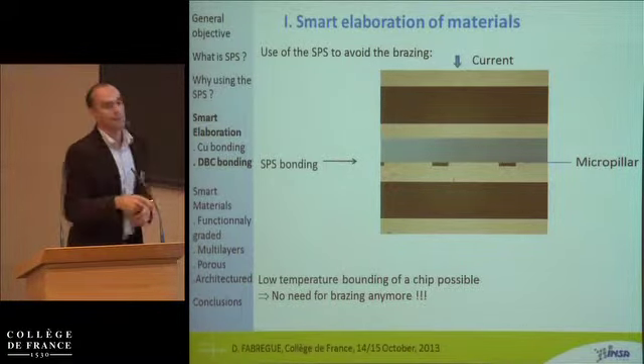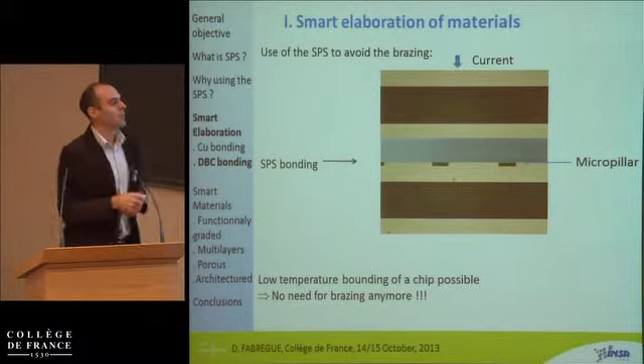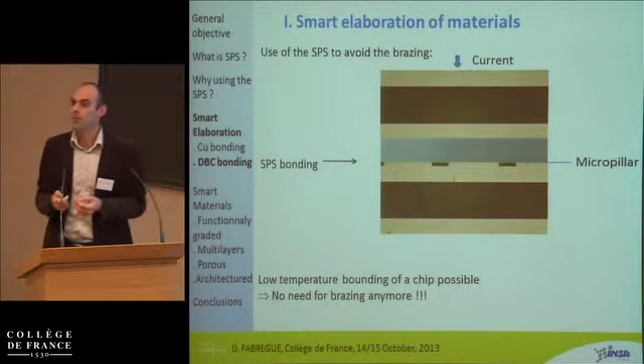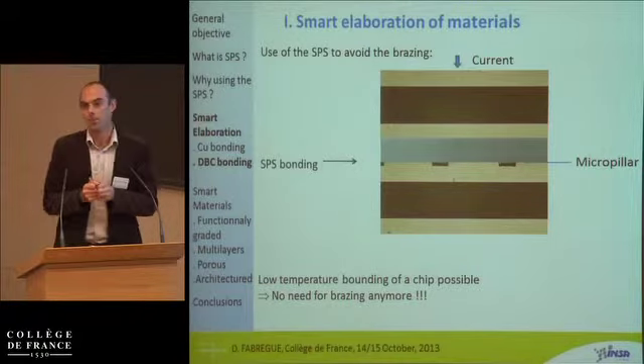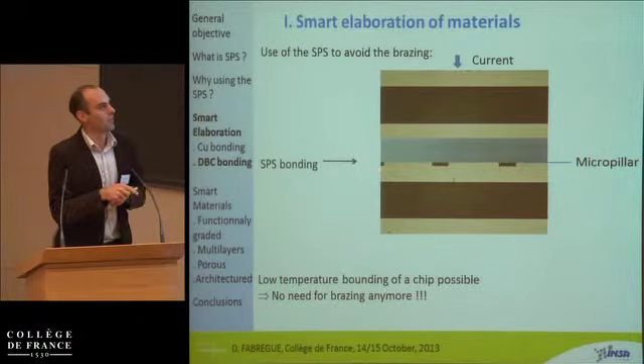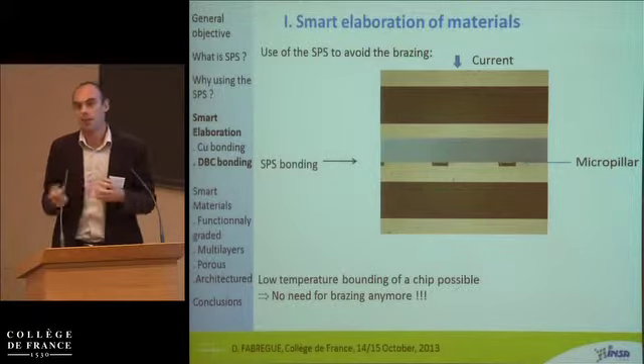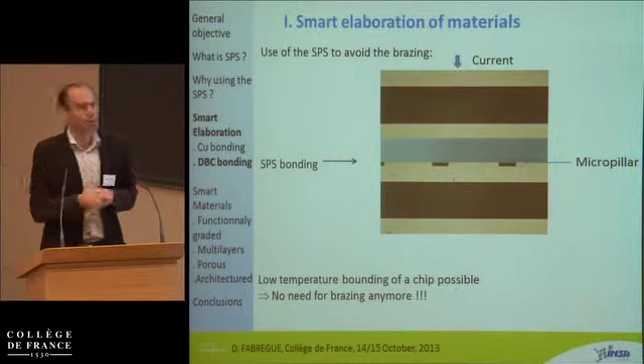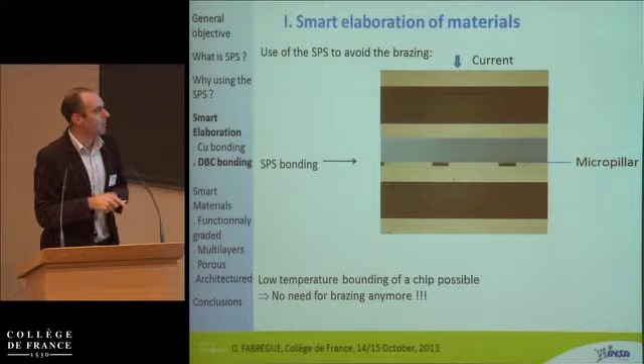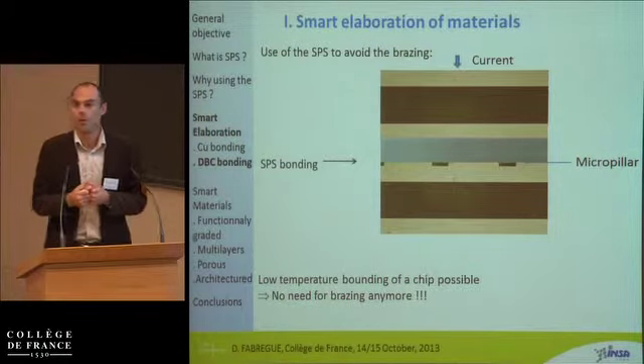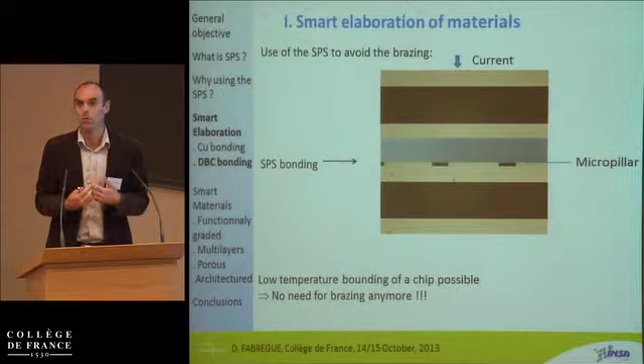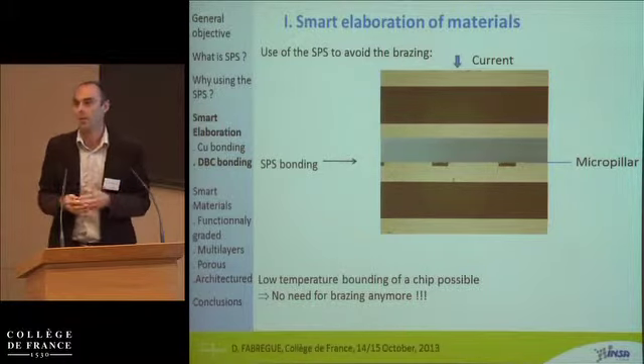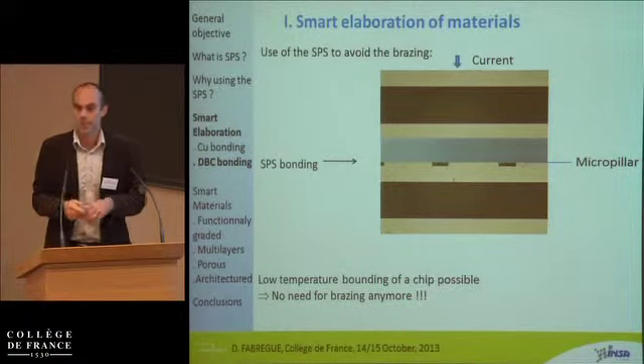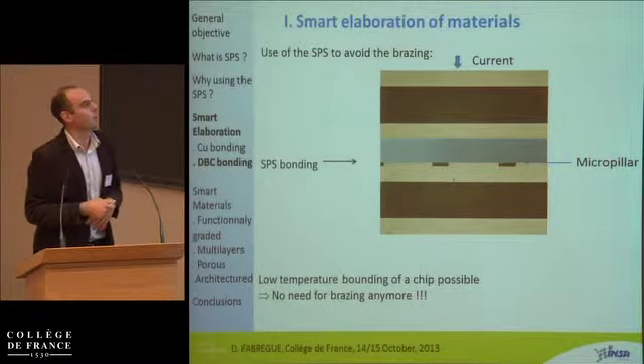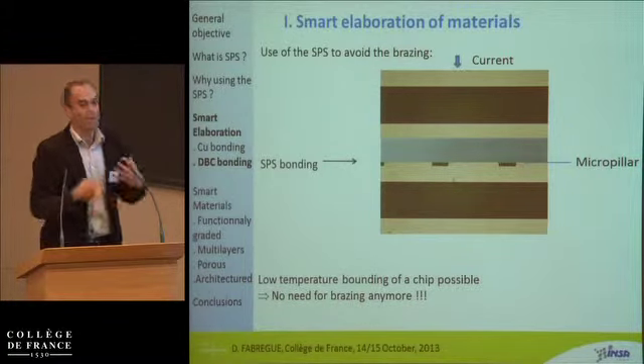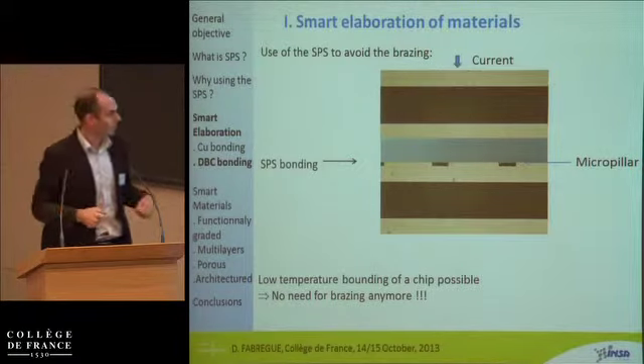So that means that the interface is really perfect. After 300 degrees C and 5 to 20 minutes, you cannot remove each part. And actually, the strength here is about the highest shear strength that you can have for this kind of application. So you can do low temperature bonding on a chip, it's possible. There is no need anymore for brazing in that case. So this is one of the topics we are working on now, by doing that at a larger scale.